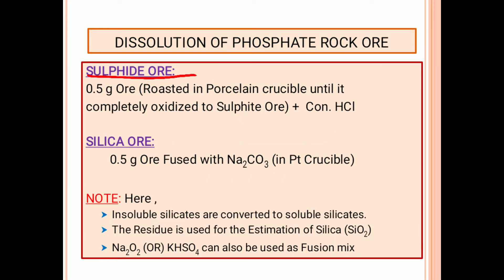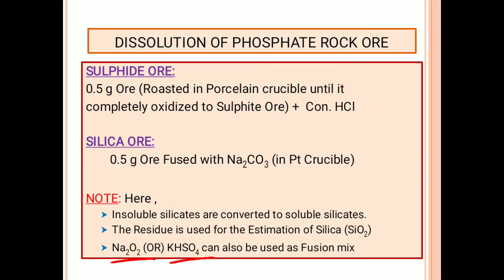If it is a sulphide ore, you need to roast it in a porcelain crucible, then add concentrated HCl solution to dissolve. If it is a silica ore, you can use the fusion technique using a fusion mixture of sodium carbonate in a platinum crucible, or you can use sodium peroxide or potassium hydrogen sulfate as fusion mixture. In fusion, insoluble silicates are converted into soluble silicates, and then the residue is used for the estimation of silica.